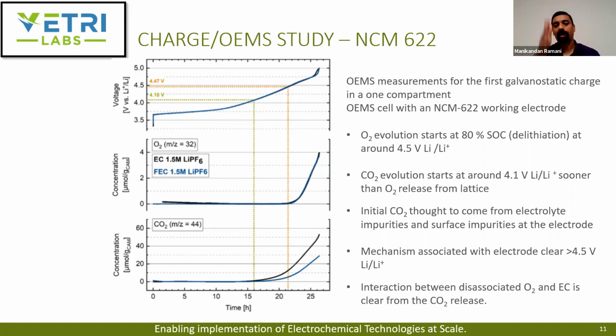But when you line it up with the oxygen and CO2, I was at least shocked to see that didn't make sense. Why would I have CO2 before oxygen? And they do explain it away with it's possibly from the electrode, but there's really no proof. They really dug in any deeper to find a proof associated with that, that it is in fact the impurity, which I could have done by taking the NCM material, or in this case, that's what they did, took the NCM cathode material and put it as the working electrode instead of the carbon in this case.